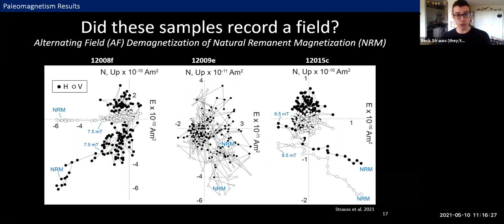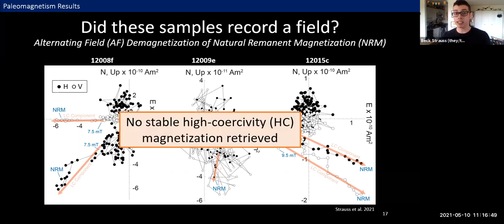At least once we remove this low coercivity component that's consistent with the kind of overprint that a lot of Apollo samples pick up, partially from being returned to Earth or just from hanging out in the Earth's magnetic field for like 50 years. Once that low coercivity component has been removed, what remains is statistically indistinguishable from cooked spaghetti. And what this means for us is that we were not able to retrieve a stable high coercivity magnetization from these samples, which is kind of a bummer.